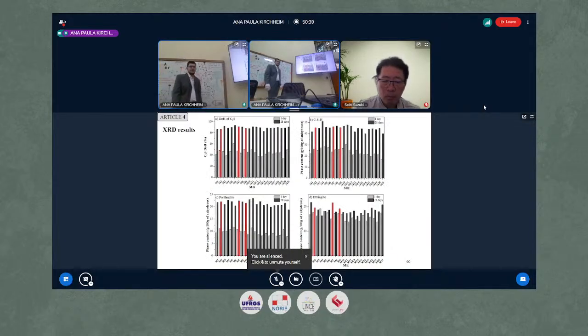Also here are the XRD results at 1 and 28 days, degree of hydration, C-S-H, portlandite and bound water, portlandite content at 1 and 28 days, and the compressive strength at 1 and 28 days. So I got all of these and tried to correlate everybody with everybody. So first of all, strength and heat correlate at 1 day, as observed in the first study in the literature, but I don't see a good relation between strength and bound water, because I have different clinkers with different mineralogical compositions.